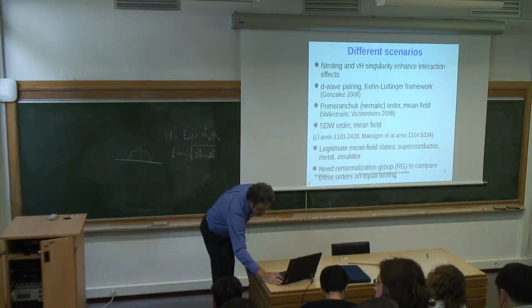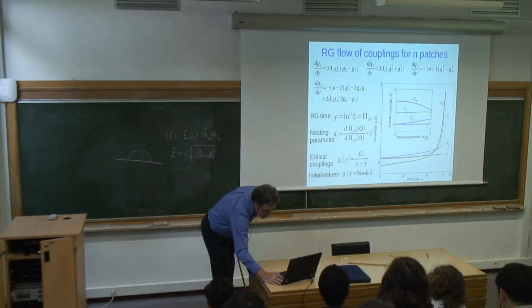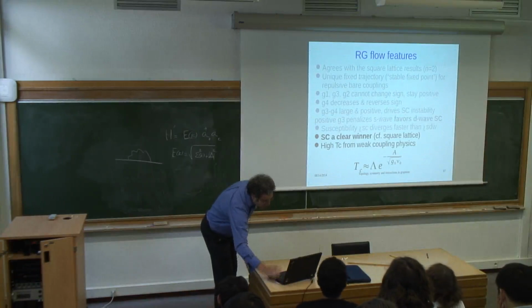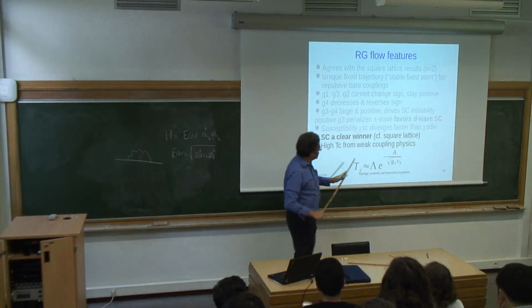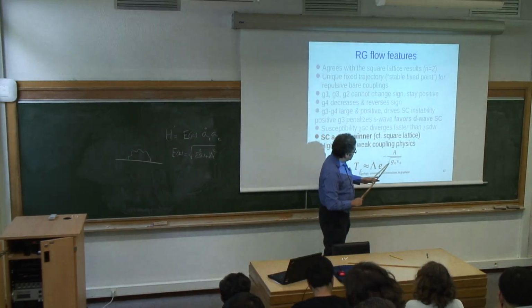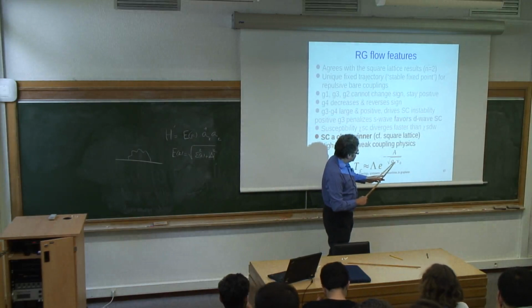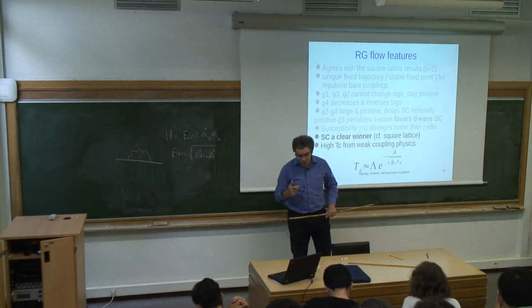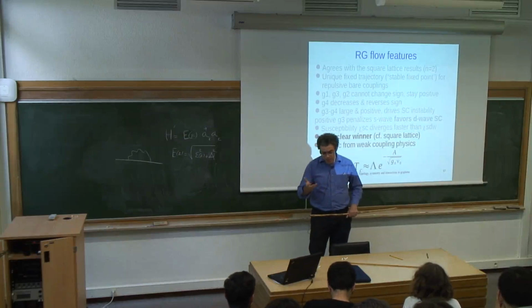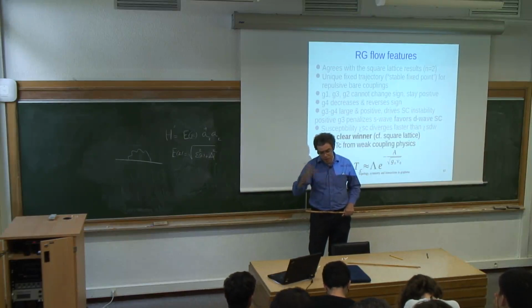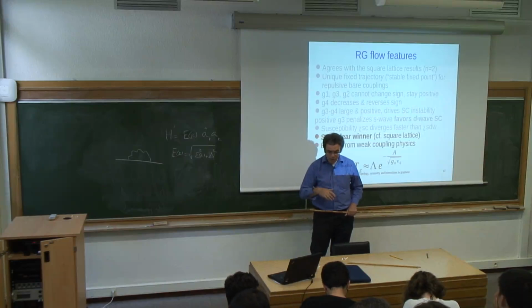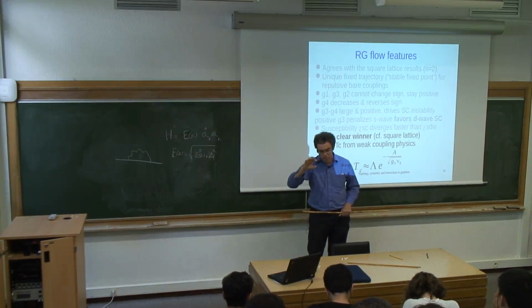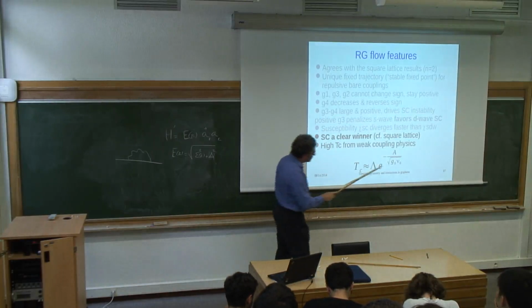no time to write on the blackboard. Let me just show you what this is like. So you get a formula for Tc where instead of the interaction strength, there is a square root of it in the exponent. The reason for the square root is that if you do the same calculation as we did to derive the BCS formula, there will be two log divergences, one from this integral over epsilon that we discussed, and the other from the Van Hove singularity. So your equation will look not like 1 equals coupling strength times a log, but 1 equals coupling strength times log squared. And so you get a BCS-like formula, but with a square root in the exponential.